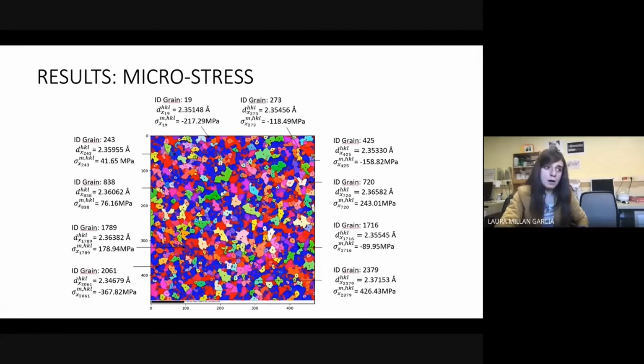The following results are obtained using the localization of the grains in the electron backscattering diffraction map. We can identify each grain because we have the information about its mass center, the X and Y values. In addition, we can calculate the microstress of each grain using the best expression of the lattice spacing obtained by genetic programming. An interesting finding is extracted from these results. Low stress in 111 large grains appears with soft neighbors, and high stress in 111 small ones with hard neighbors. We are analyzing this hypothesis because it's very important in our study.